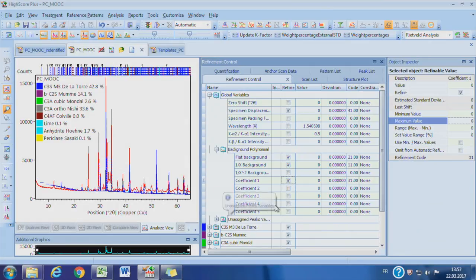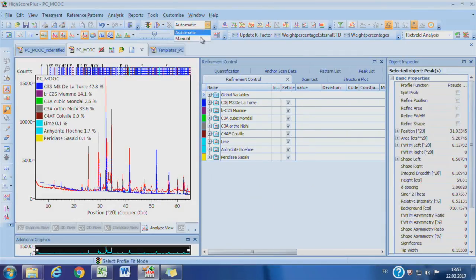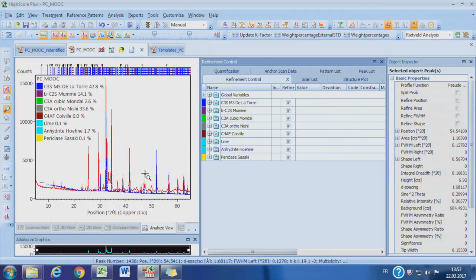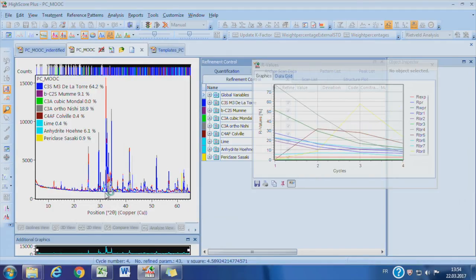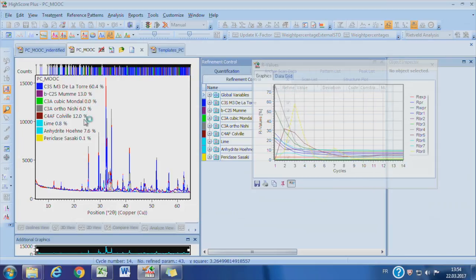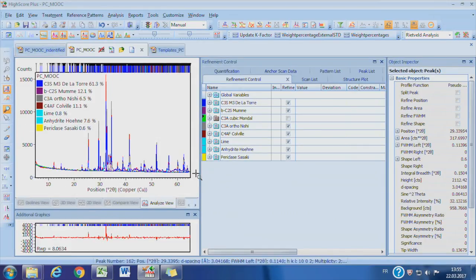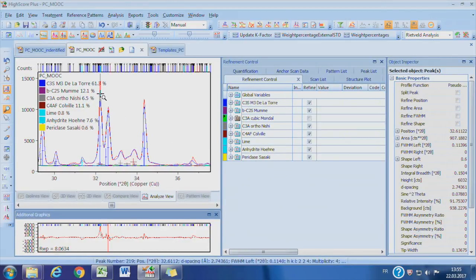After all parameters are set, the refinement can be executed by pressing the refine button. After the first run, we can see there is not much cubic C3A in the cement, so we can remove it for further refinement. As we have so many phases in cement, it takes several runs to reach the global minimum. Open the additional graphics for the difference plot to visually check the fitting. The most common mismatching is from the cluster of peaks around 32 degrees, where we have the main peaks for C3S and some other overlapping peaks. The mismatch is mainly because of the preferred orientation of C3S. We can find out the direction by pointing the mouse onto the peak that is not well fitted — here it is the 0-6 plane for M3 alite.